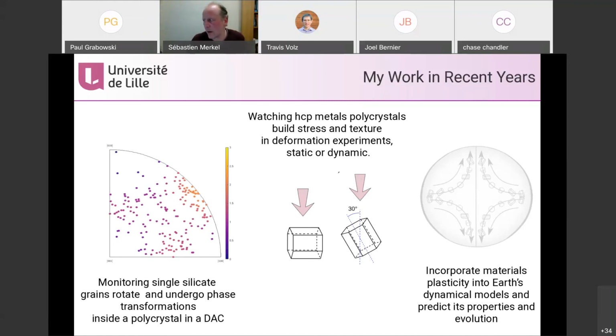So usually the way we do it is with global mantle flow or inner core flow. They are very simple models based on fluid dynamics with a constant viscosity or something like that. We use the flow from those geodynamics models and couple it with a viscoplastic self-consistent calculation to calculate the microstructures. So it's not the microstructures driving the flow or giving constraints on viscosity. We just put in an ad hoc viscosity.